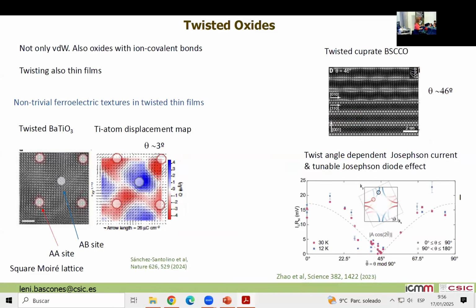So normally when you have the two cuprates, because it's a D-wave superconductor, if they are at 45 degrees, the Josephson coupling is not expected. And somehow they see that it's very strongly suppressed, but not completely suppressed at 45. In fact, what they are observing is tunneling of several Cooper pairs, what they call higher harmonics. And then they play in all these regions. So somehow this 46, you see here, all these points have many angles.